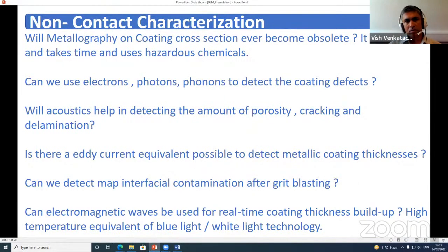So speaking about non-contact characterizations, can we do away with metallography? It takes a lot of time, and it uses some chemicals, acids, etching. And mounts are made out of epoxies. If we can do away with that and use a non-contact method, much similar to what we do for eddy current analysis of top coat TBCs. Is it possible to use electrons, photons, and phonons to detect the coating defects? A lot of them are actually getting industrialized. If we can use millivolts and microvolts to know if there is a coating or not, by itself, we can avoid a lot of metallography work.